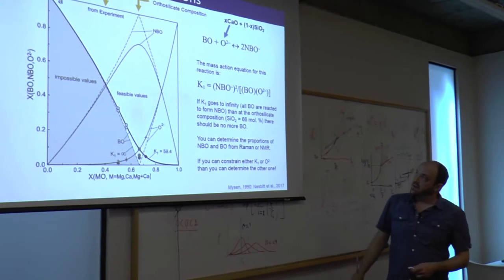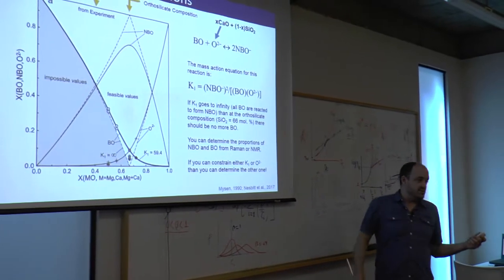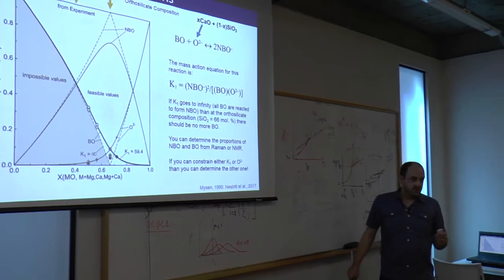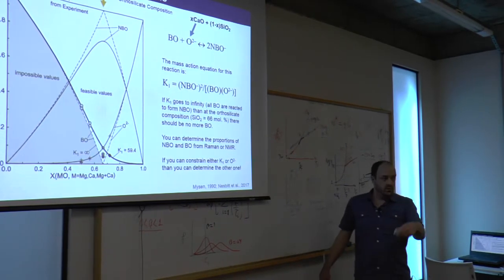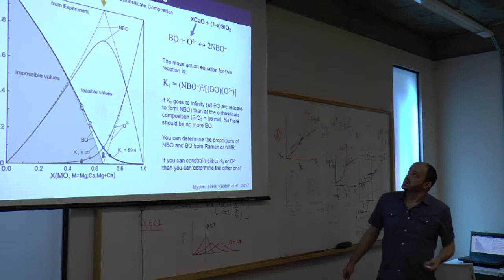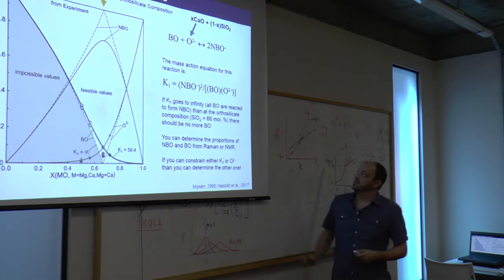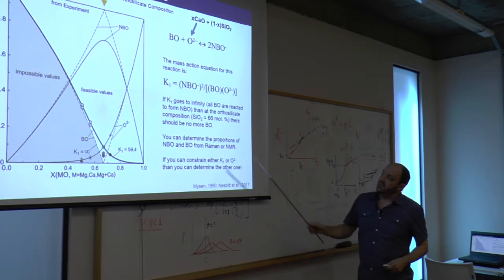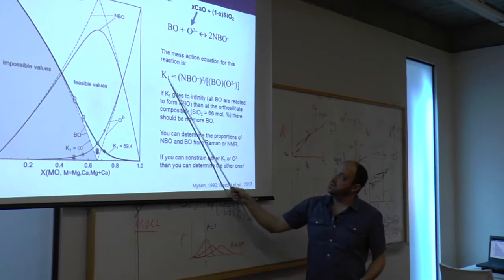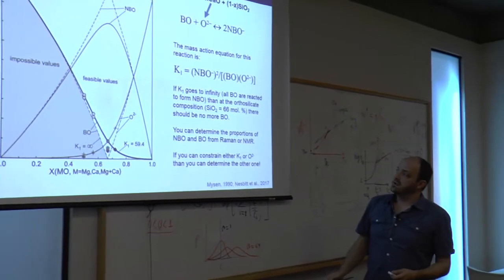And I'll show you an example of that composition, but it's whatever the modifier is, 2 times whatever the modifier to 1 mole of silica. So 2 moles of modifier to 1 mole of silica. So if this reaction doesn't go to infinity, that has a couple consequences.